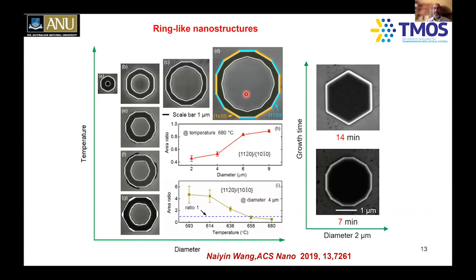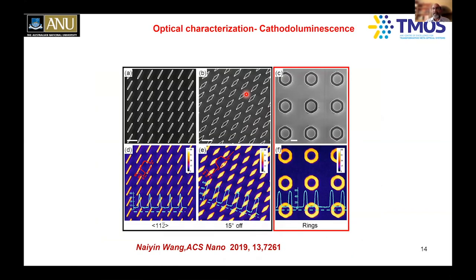In fact, Nain Wong has taken these nanostructures, the nanomembranes, nanodiamonds, and nanorings, and tried to do something called cathodoluminescence. In this case, you excite the electrons from the valence band to the conduction band using an electron beam rather than a laser as in photoluminescence, and then look at the light emission. You can see very bright light emission coming from all these nanostructures, indicating that these 4 years of hard work really paid off. You are able to create defect-free, beautiful nanostructures of a wide variety of shapes, and these sorts of structures are very useful for making devices, which I'll come back to and share.